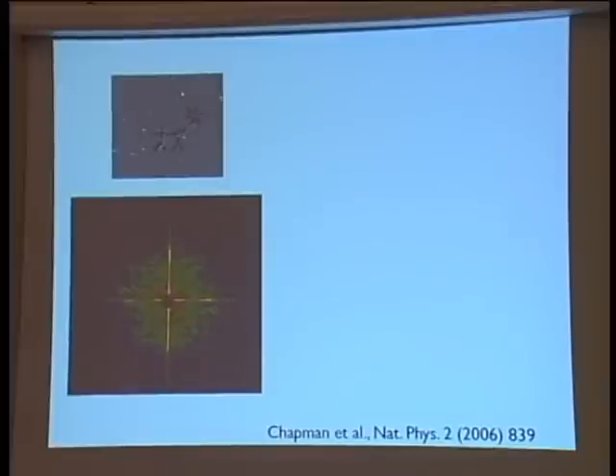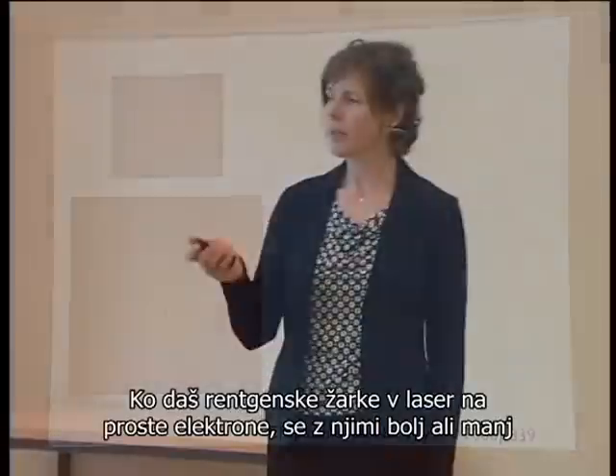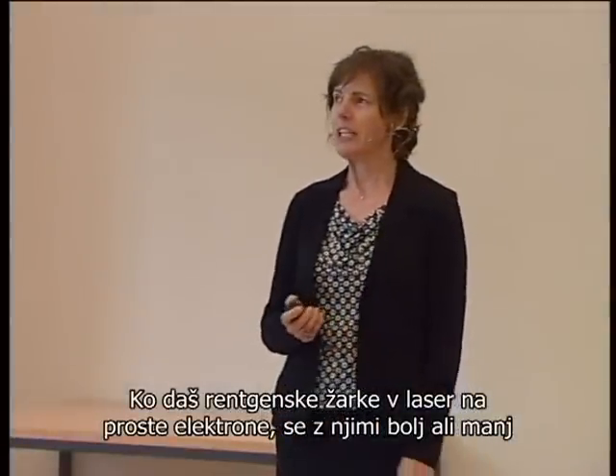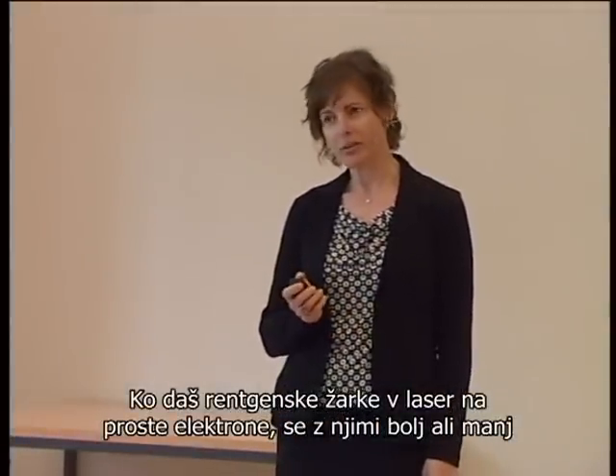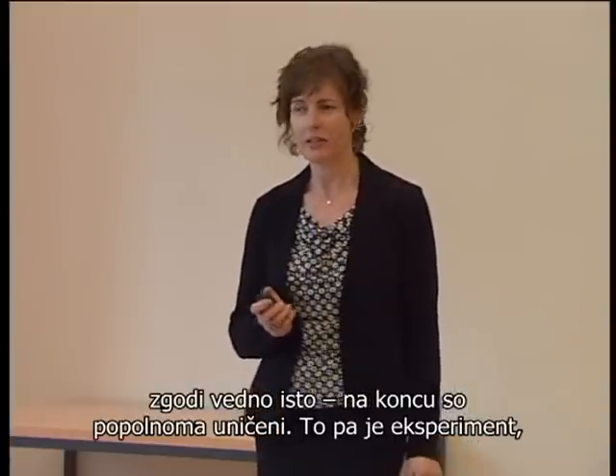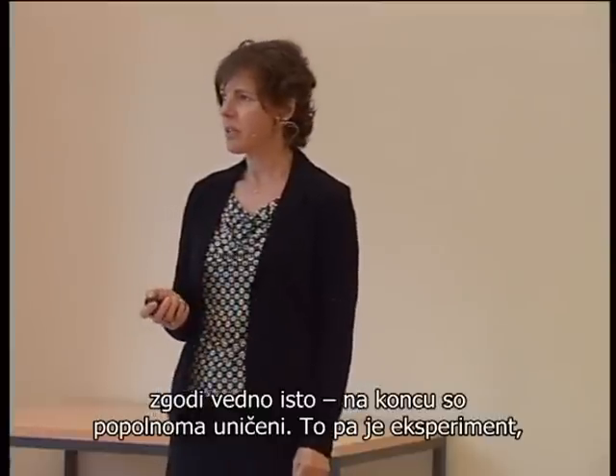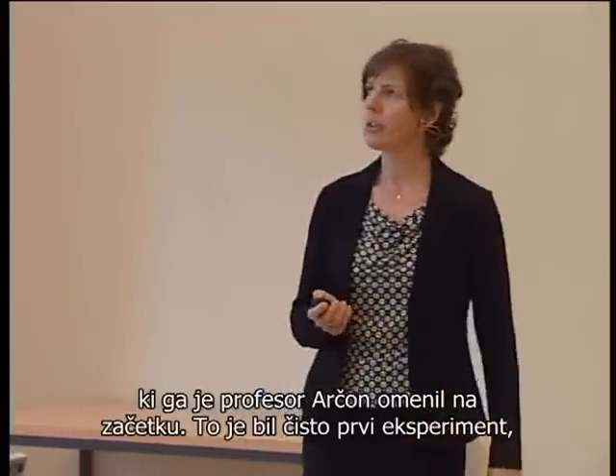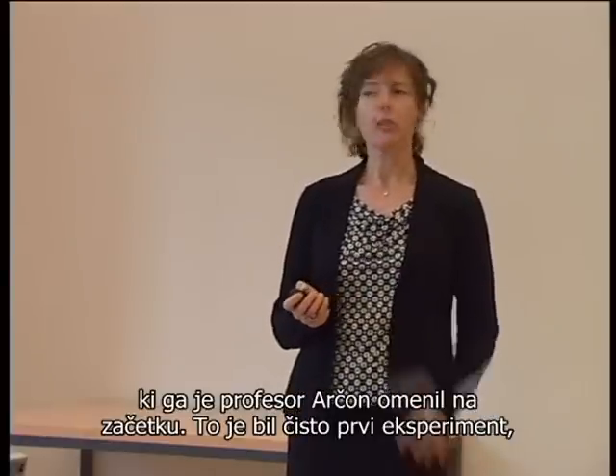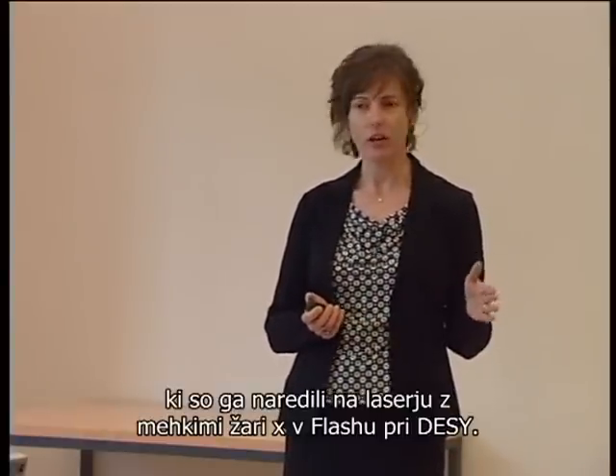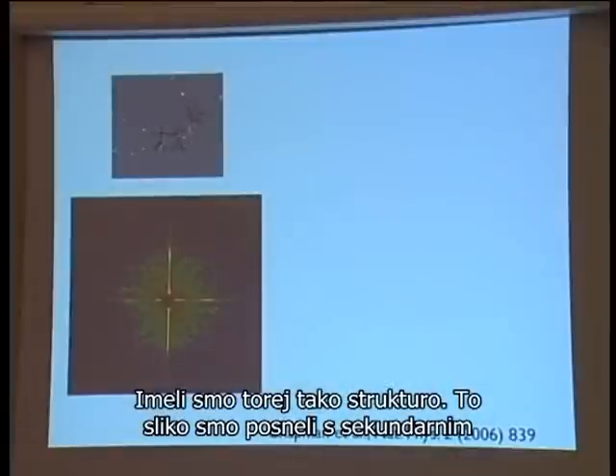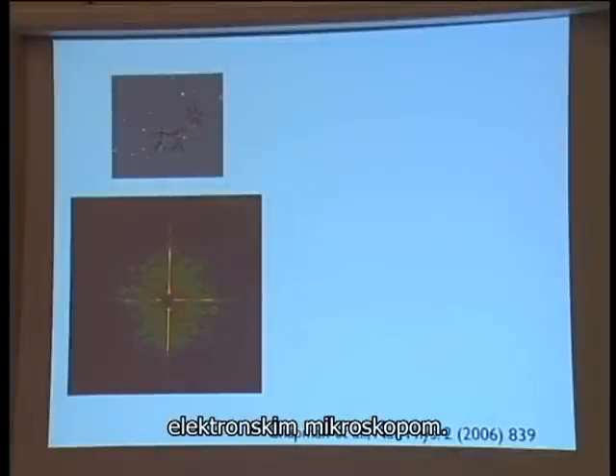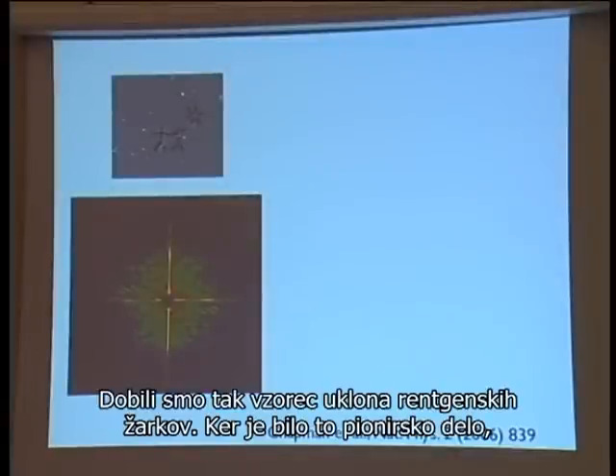So, when you put X-rays into a free electron laser, what happens to the sample is that pretty much always it gets completely destroyed. This is the experiment that Professor Archon mentioned at the start. It was the very first experiment done at the soft X-ray free electron laser FLASH at DESY. We had a structure like that. This image was taken with a scanning electron microscope, and we obtained with the very first shot this diffraction pattern.